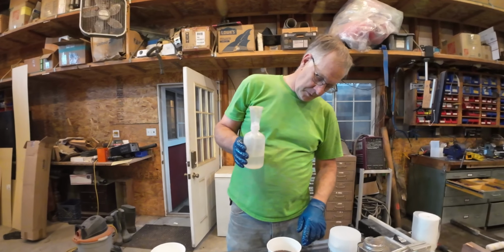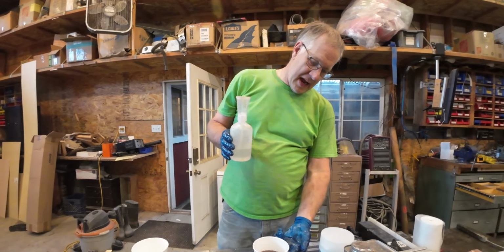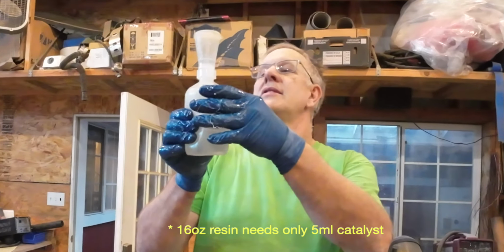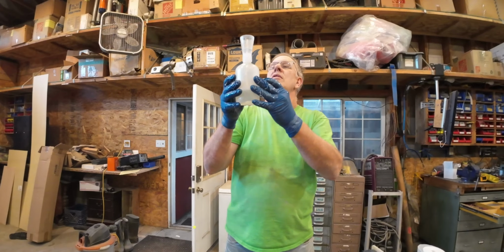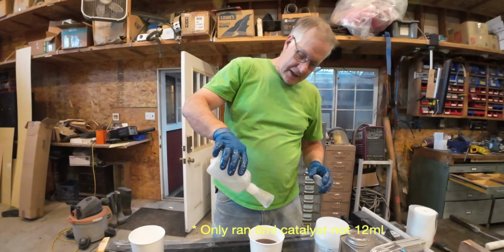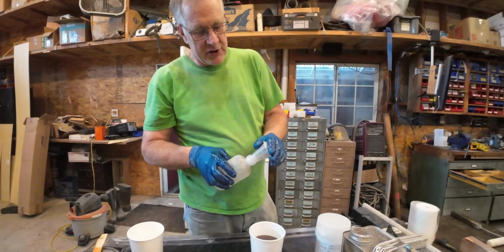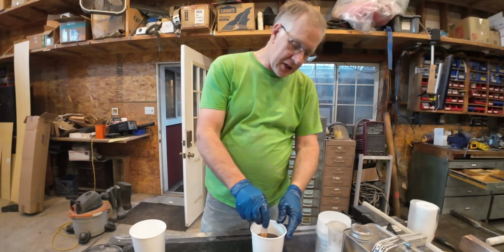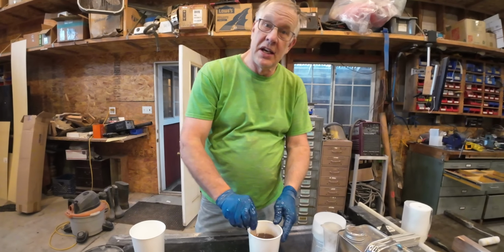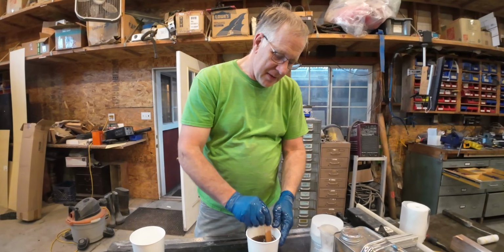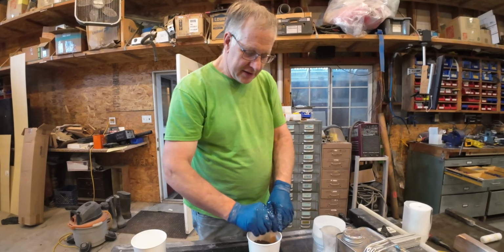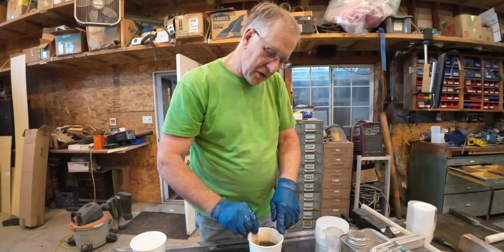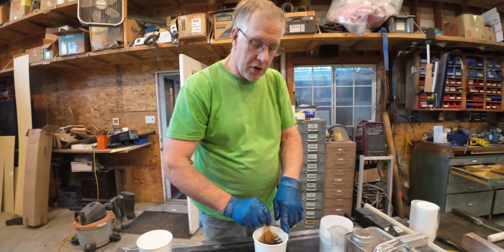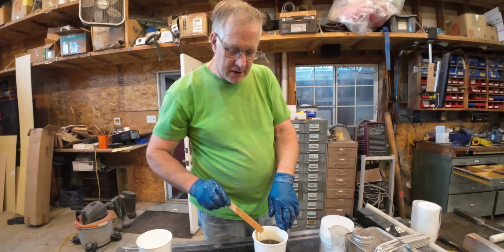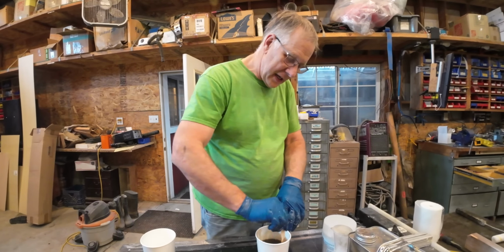So this is a 32-ounce cup. Half is 16 ounces. I'm a little over 16 ounces. It takes about 10 milliliters of catalyst to catalyze that much resin. I'm going to run about 12 or so milliliters into this, which is going to make about a 1% catalyst ratio, which is pretty typical today. The temperature outside is about 70 degrees, which is how you use your catalyst to adjust to temperature. If you're at 70 degrees, 1% catalyst is fine. If it's colder, you should probably go a little bit more than 1%. This morning I was using about 1.25% catalyst because we want the resin to cure a little more quickly and a little harder.